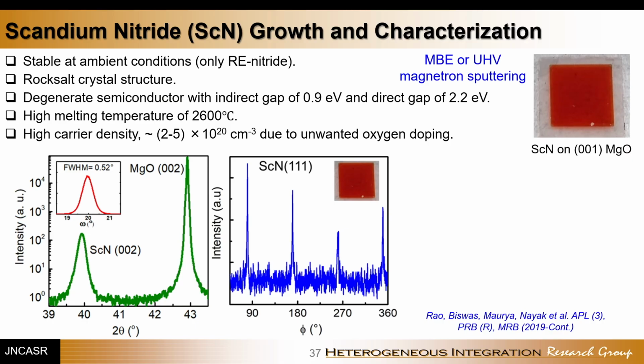It's a 3B nitride semiconductor. Instead of 3A nitrides, which are gallium nitride, indium nitride, and aluminum nitride, this is a 3B nitride. It's stable at ambient condition. And it's the only rare earth nitride, if you take scandium as a rare earth, that is stable at ambient temperature and pressure. It has a rock salt crystal structure, an indirect gap of 0.9 eV, a direct gap of 2.2 eV, and a high melting temperature, similar to all other transition metal nitrides.